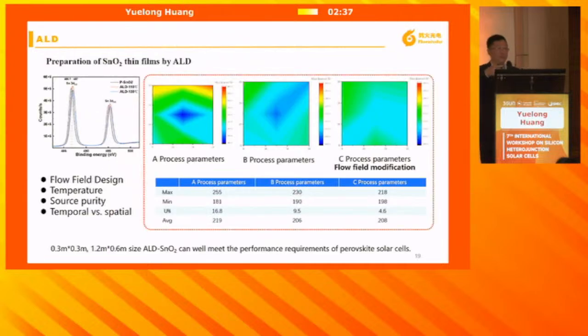Of course, professors said tin oxide should be replaced, but in fact, we can make it at a reasonable price with ALD. It's affordable to deposit by ALD. You can make a very good film with good homogeneity, but what's very important is that using tin oxide deposited by ALD, you immediately have very good encapsulation. It's very stable. Even without lamination, we kept it in air for half a year and nothing happened. So depositing very good tin oxide with ALD is very important.